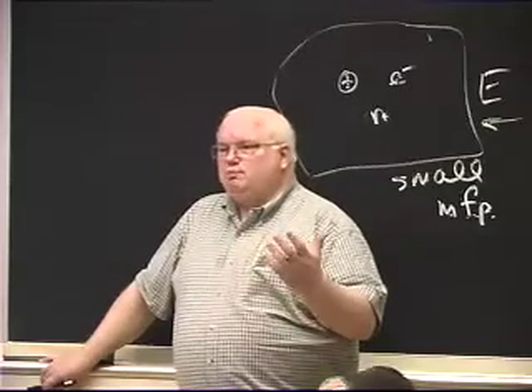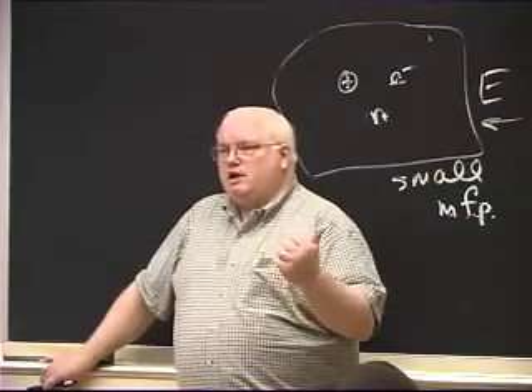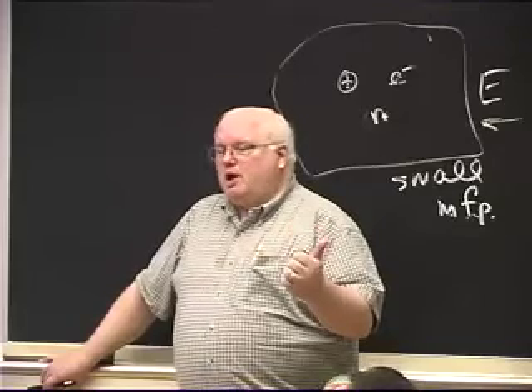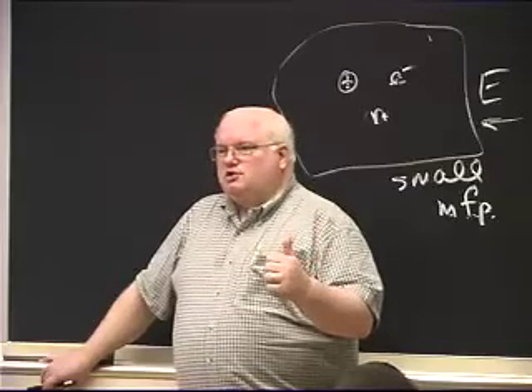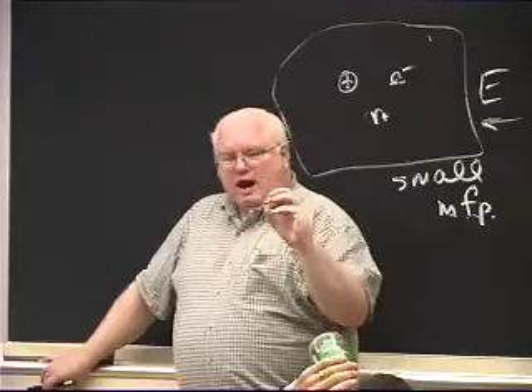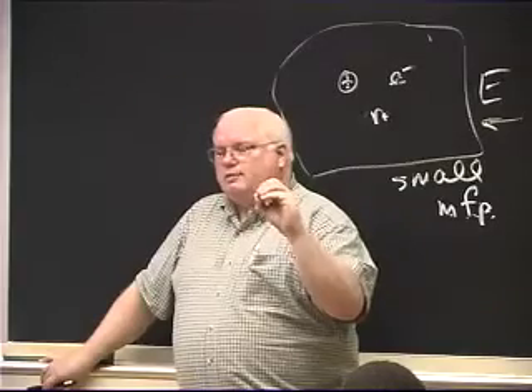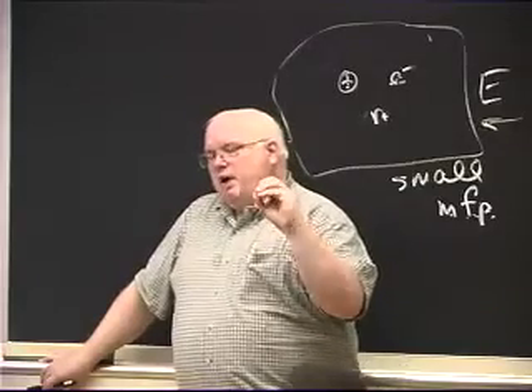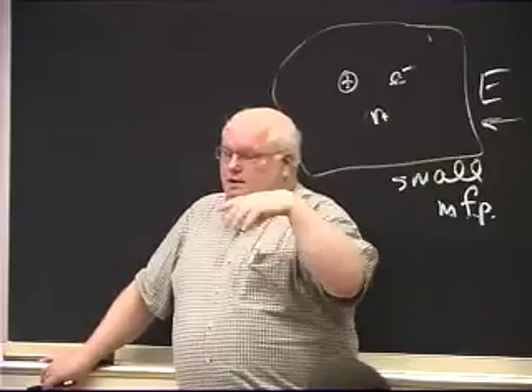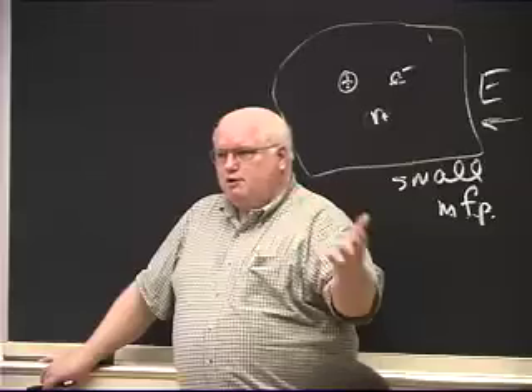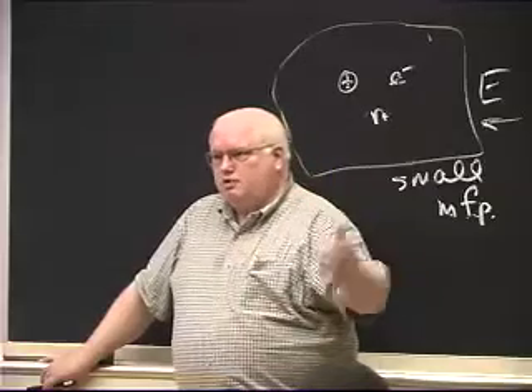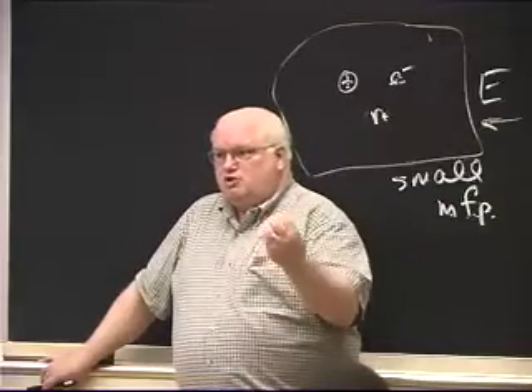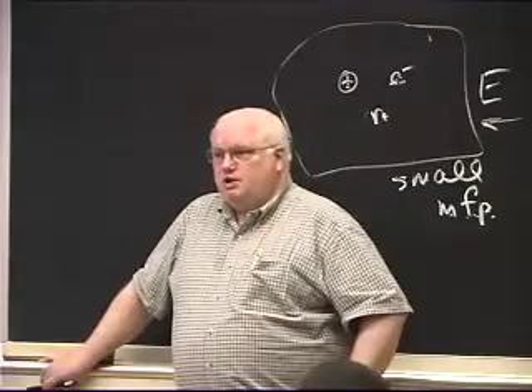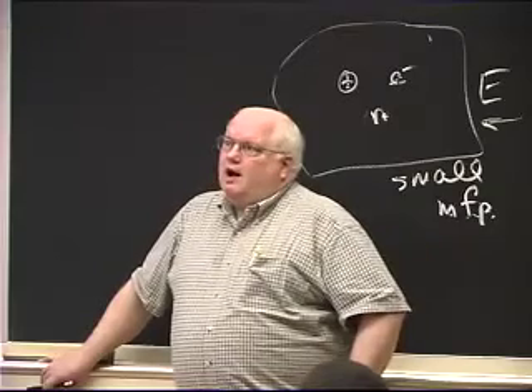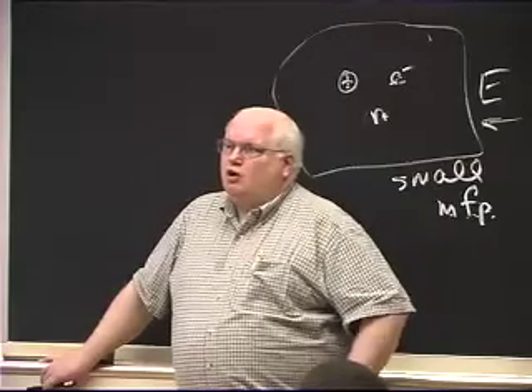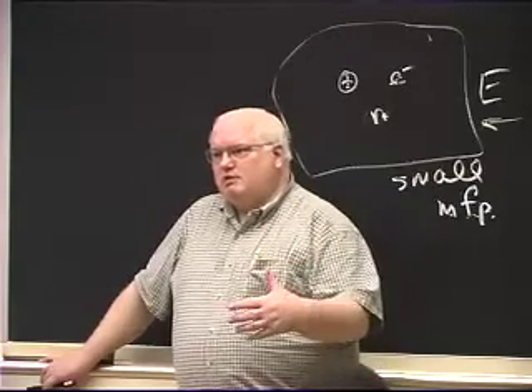And what he was doing is burning off the cellulose, and cellulose is a hydrocarbon, and it forms carbon monoxide and water vapor in the oxygen. And as it burns, if you analyze the gas in that arc, you'll find it's about 60% hydrogen and, I can't remember, 5 or 10% water vapor and 10% carbon monoxide and 5 or 10% carbon dioxide. But basically, you exclude the nitrogen by burning up cellulose, okay? And that's the origin of the E6010, 6011 electrodes.